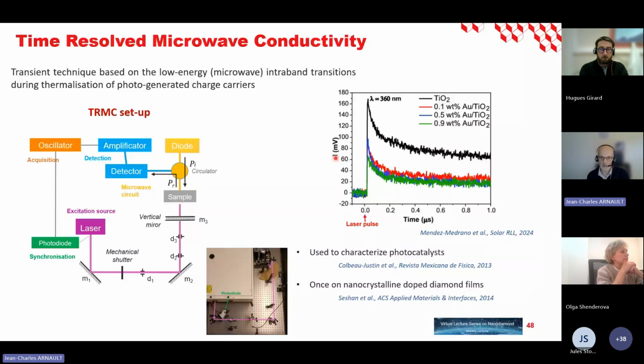So this is a typical curve obtained for other photocatalysts, TiO2 for example. At time zero, you have the laser pulse. You will initiate charge carriers here with this intensity peak. And then versus time, you are able to monitor the dynamics of carriers, with recombination or trapping in the material. So this was and is frequently used to characterize photocatalysts. And in the literature, we were able to find only one study using it for nanocrystalline diamond films. So what will this technique give on the nanodiamonds we have prepared before, and with the performance Hugues showed just before?